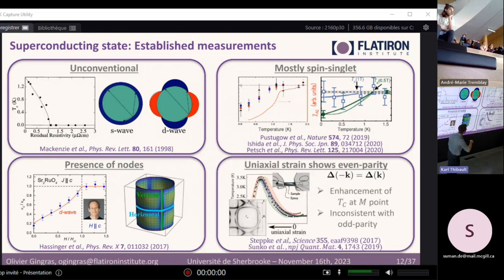And finally, here, what is well known is that when you apply uniaxial strain on the material, you will see the critical temperature shoot up by a factor of more than 2. And this is explained by the fact that when you apply pressure, the Fermi surface expands toward the zone boundary where there's a Van Hove singularity, which means that there's a lot of states available for pairing.